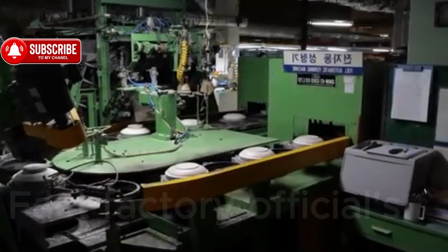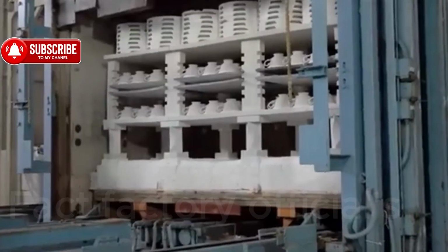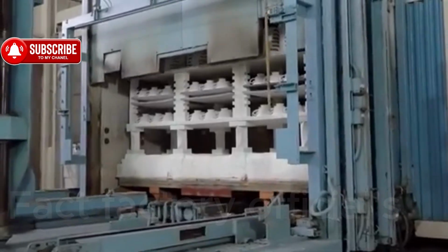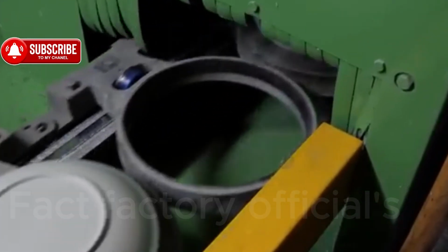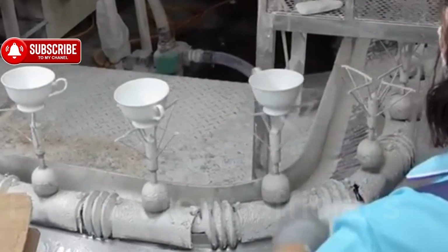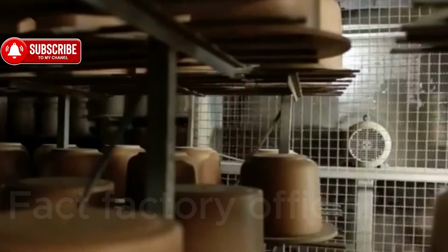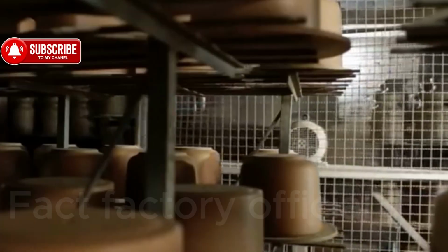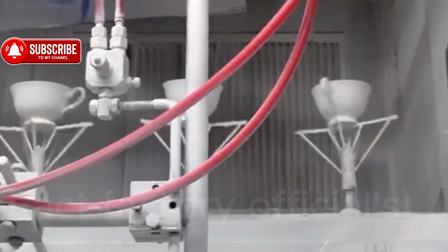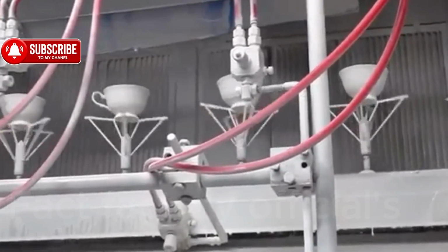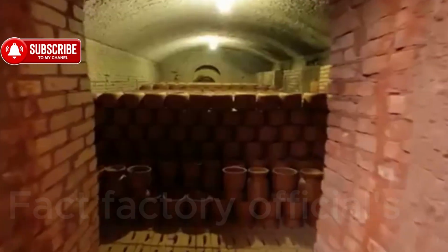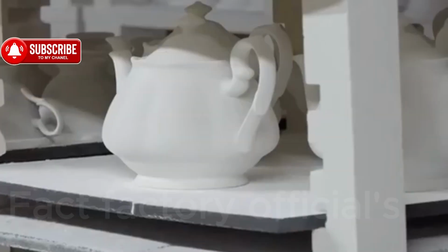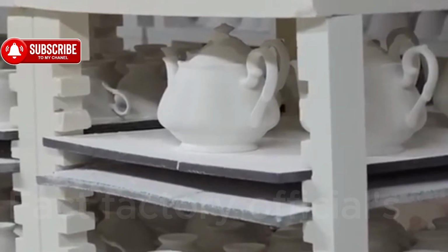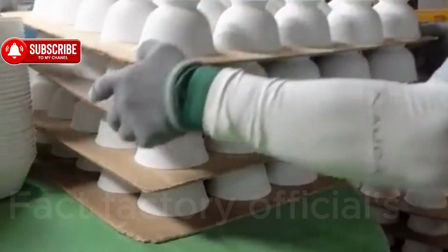The dried ceramic pieces, now structurally stable, are sent directly into the kiln for their first firing, known as the bisque firing. The goal at this stage is not to achieve maximum hardness, but to remove all remaining bound water and organic impurities. As the temperature gradually rises, the mineral particles begin to tighten and fuse slightly, forming a temporary but solid framework that still retains enough porosity for the glaze to adhere firmly later on.